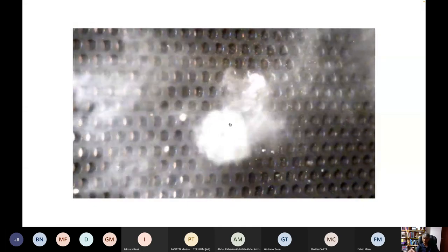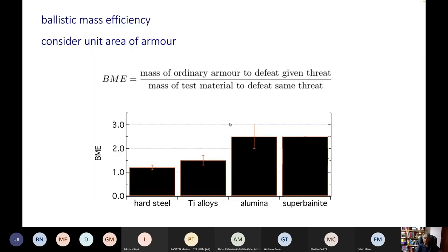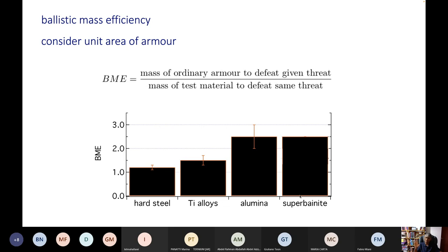There is a backing plate to contain the debris. The purpose is to destroy the projectile, because even the edges of the holes help to destroy it. If I show you the parameter known as the ballistic mass efficiency — this is the mass of ordinary armor to defeat a given threat divided by the mass of the test material to defeat that threat, and the higher this value the better — this is the conventional armor steel, these are titanium alloys, and alumina can also act as armor but it can't take multiple shots. And this is our super bainite when it contains those holes.